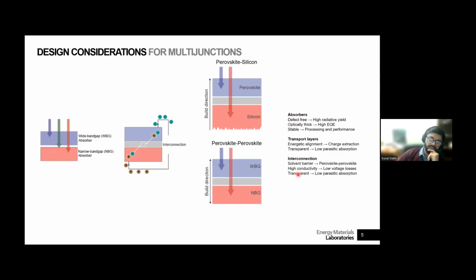So what you're looking for is, in the absorber, a high radiative yield, so preferably a defect-free layer or defect-poor layer. Perovskites are never defect-free. You're looking at a layer which is thick, so that you can get a very high EQE, and that means that because these layers are series connected, you need the current by each of these layers to be the same or close to each other, in order to not lose any JSC. Otherwise, the subcell with the lower current determines JSC. So ideally, you want them to be as thick as you can make them, and that results in a high JSC in both of them.